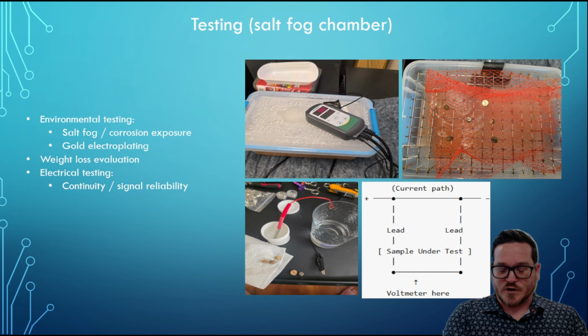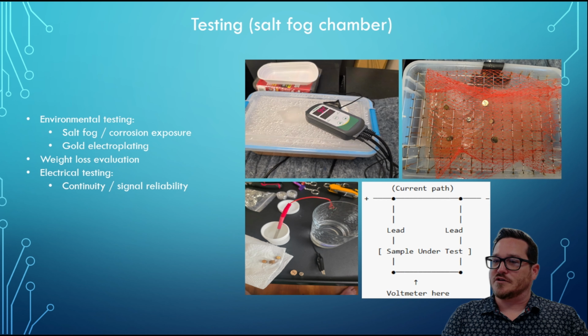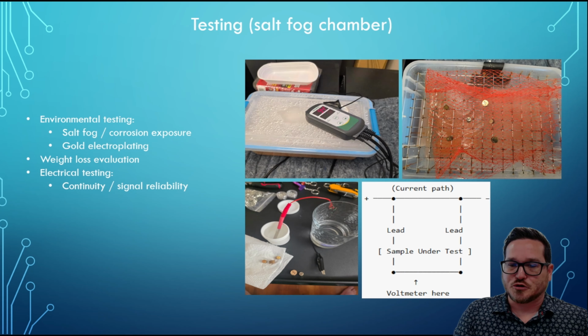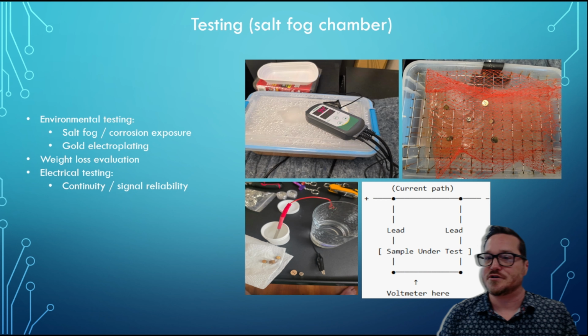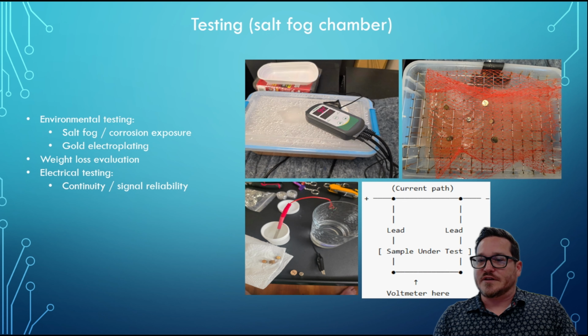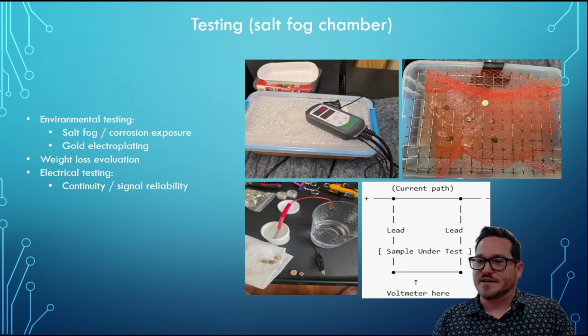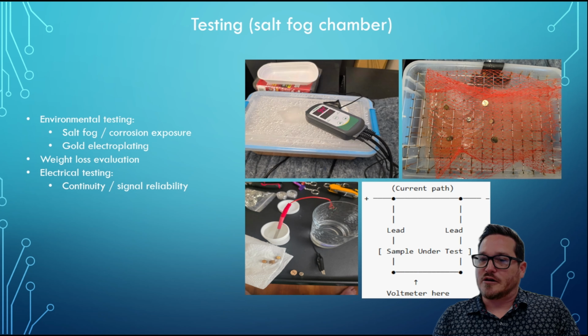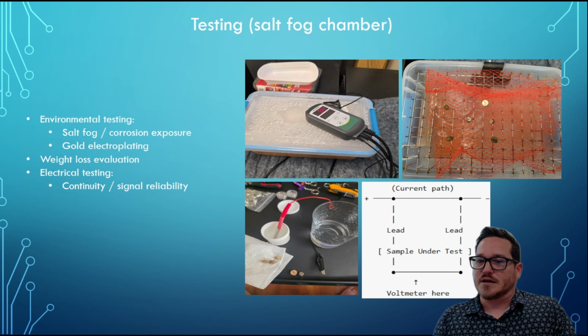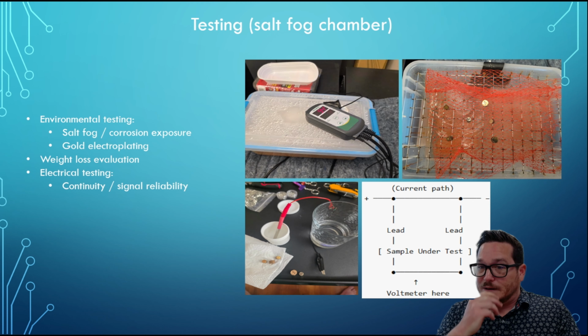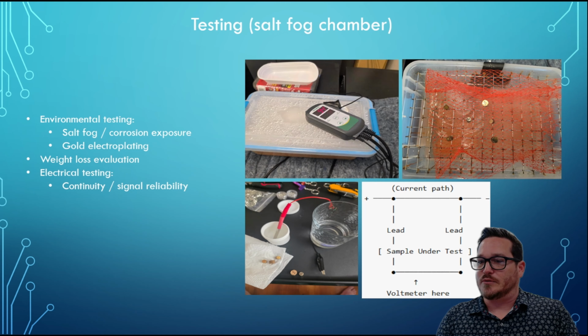One of the sets of 3 I left as they were. The other set of 3 I coated in gold using a gold electroplating kit, which you can see in that bottom left picture. This works basically by you have a heated gold solution, which is in that little white tub there, and you put the positive lead into it. The negative lead has a little alligator clamp, and you hold the metal sample with it and then dunk it into the solution. Once electricity is applied, the gold in the solution adheres to the surface of the metal sample.